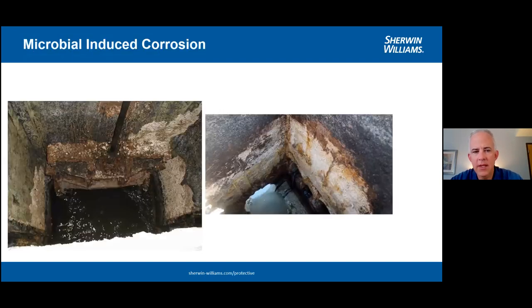Took a couple photos here, and these are a few years old. But if you look at the structure on the left, it is a gate going into a wastewater treatment plant. If you can see this carbon steel gate here, and the level of steel degradation, the rust, the corrosion, the pitting that has occurred on this structure, this gate here is only about an 8 or 10 year old structure. That was not a very old structure.